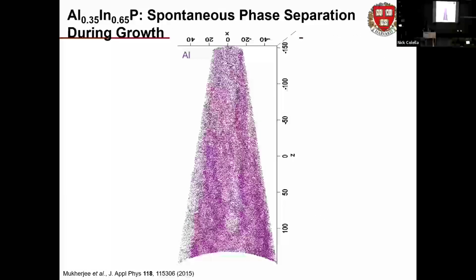So we do atom probe. Here we go. Here's a slice through an atom probe data set just showing you aluminum, and you can see right away there's some substantial difference in the amount of aluminum from one spot to another. Actually, quite a lot, like a big difference in the amount of aluminum between here and there. These are all aluminum atoms drawn in purple. Why couldn't we see that in the TEM?